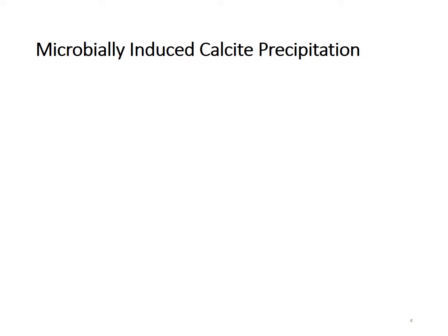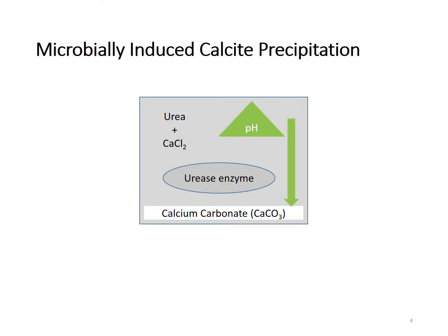Microbially induced calcite precipitation is a biologically induced mineralization process and is a classical example of cementation and genesis of calcareous rocks in nature. Researchers have attempted to mimic this process in a laboratory under controlled conditions with a view to employ it as one of the ground improvement and ground creation techniques. As a consequence of microbial metabolic activity, calcite precipitation occurs. Enzymatic hydrolysis of urea by microbes is the most commonly adopted technique among various other techniques available.